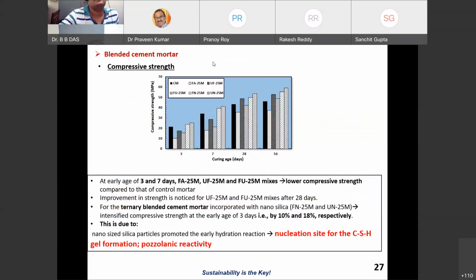Now this is my compressive strength. Just for understanding, the advantage here is at the early age, 3 and 7 days. You can see the results at 3 and 7 days for fly ash and ultrafine fly ash. Even the fly ash ultrafine mixes have lower compressive strength than the control mortar. We know it very well. When I am going with secondary cementitious material, I have to compensate for the early age compressive strength.